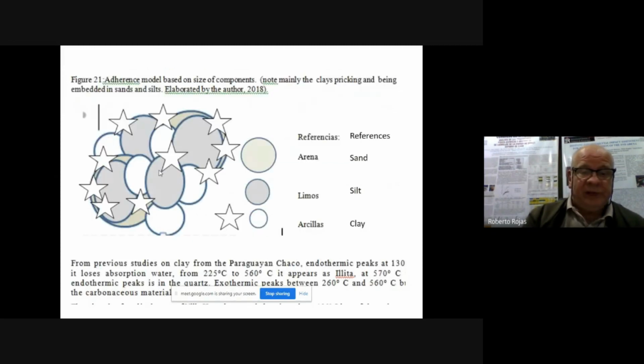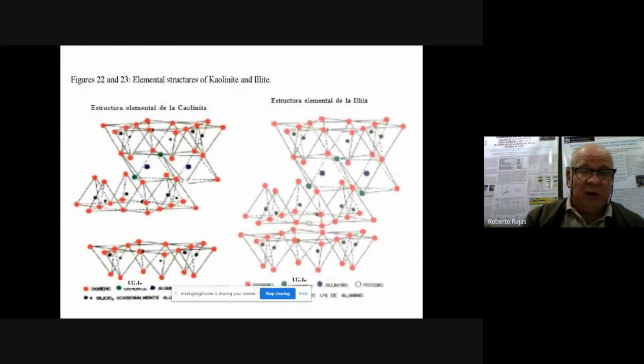So here we have the small pieces of clay getting inside and picking the sand and also the silt. They are inside and outside and uniting the sizes, all the sizes. Well, here we have a kaolinite and an illite. Illite is from the Chaco and kaolinite is from Tobati. There is a small difference here that depends on the aluminum hydroxide that also unites these particles here at the illite.